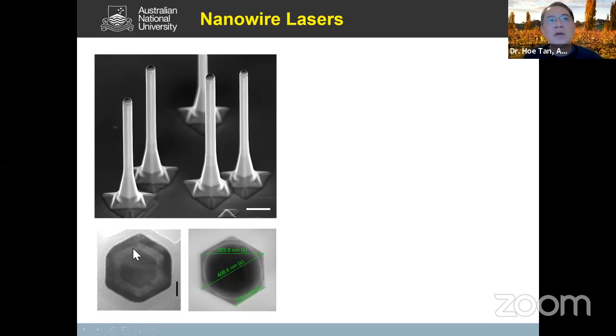But what we also do is we cover the gallium arsenide nanowire with an aluminum gallium arsenide shell. The reason for that is aluminum gallium arsenide has a larger band gap, so it essentially encapsulates the carriers in the core region. In addition to that, it also passivates the surface of gallium arsenide.